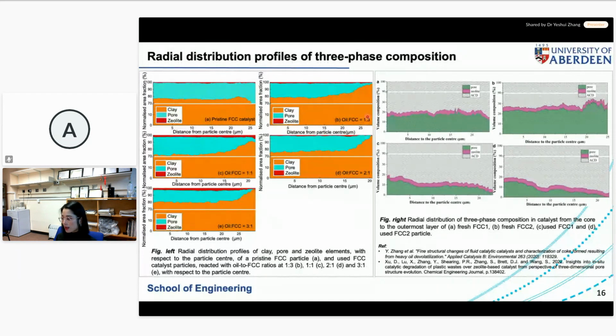What we can summarize is that you can see the surface being blocked, either by the clay or by other materials formed at the surface, blocking the surface pores. That's why there are fewer open pores at the surface of the particle. But there is no change in the zeolite distribution. That's one of the key findings of this piece of work. The right-hand side figure is another continuation of this study.